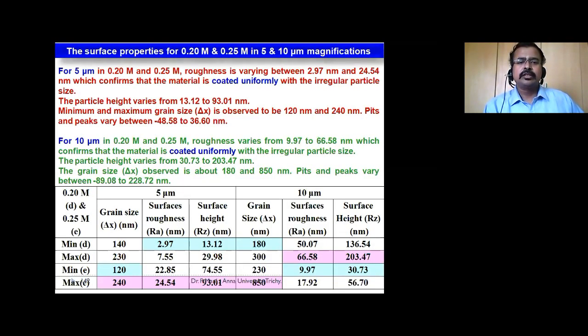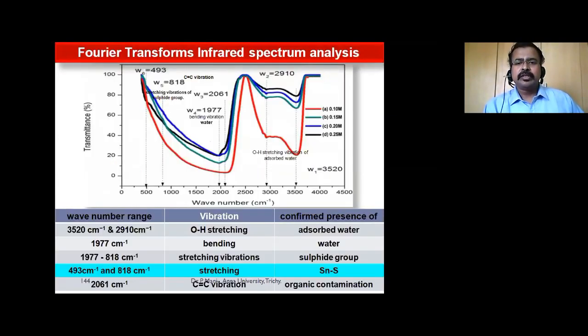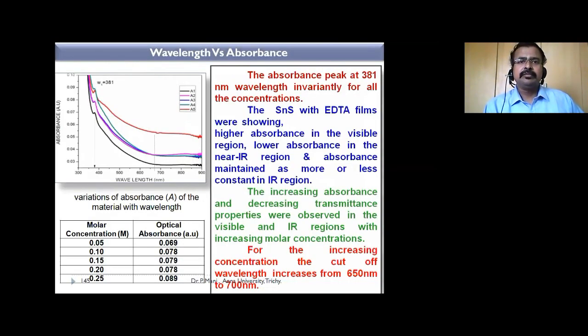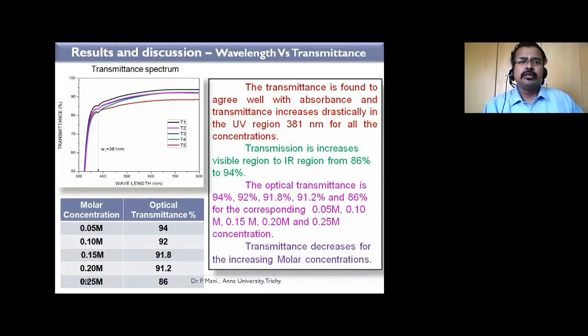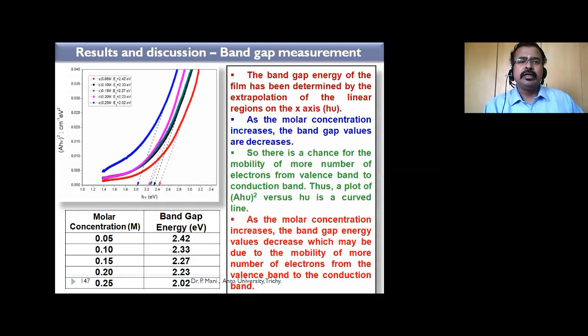FTIR analysis confirms the presence of water, sulfide group, organic contaminations, and we are seeing absorption spectra, wavelength versus transmission. It is ranging between 86 to 94%. Band gap for EDTA added tin sulfide is 2.02 to 2.42 electron volts.